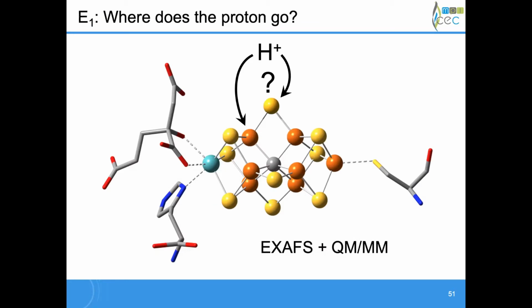Okay, that helps. The second question is this E1, which you compare with cryo-reduced: how was that one produced? E1 is produced by putting it in turnover with a very, very small amount of iron protein present. It reaches a steady state, and we do quantification by EPR. The E0 state is EPR active, E1 is EPR silent, and E2 is EPR active. So you can track your sample composition for E0 and E2, and whatever is not E0 or E2 should be E1. Okay, and do you know what the percentage is? It's about 50%. All of the spectra I've shown you have been corrected for that E0 contribution.